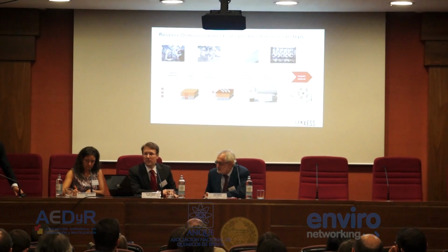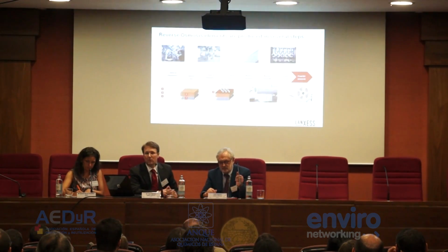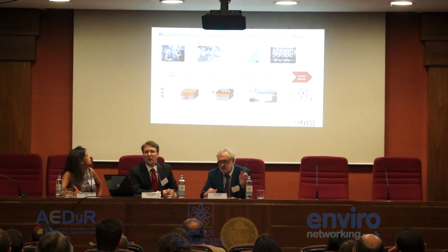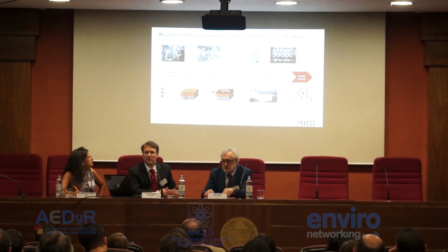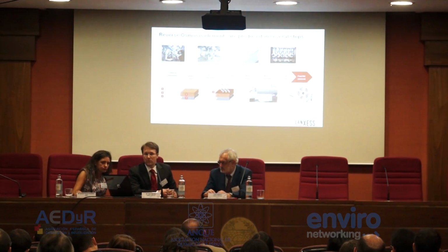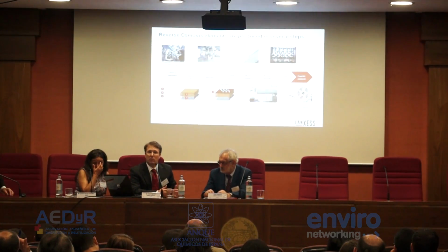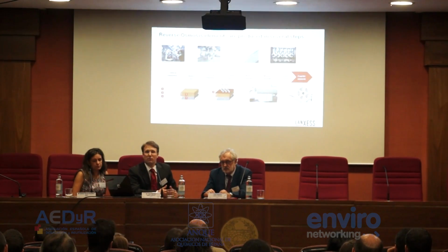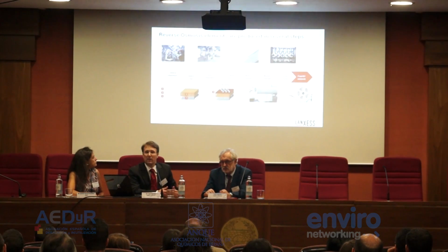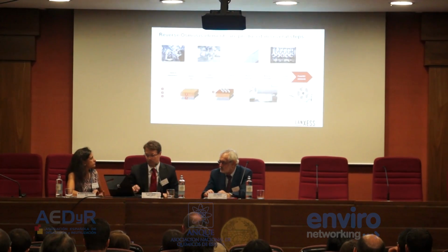So for almost 3 years we have been producing reverse osmosis membranes in Germany, around 100 kilometers south of Berlin, and we're producing a composite membrane based on a polyamide layer. We cast the polysulfone layer on the non-woven material. Then we run a polymerization process where the PA is polymerized on the polysulfone to form the selective layer. And then we have a fully robotic winding procedure to finally make the spiral wound modules. So we are the only producer in the European community making both the membranes and the spirals.